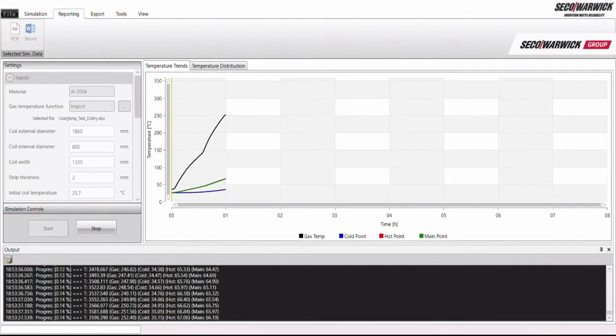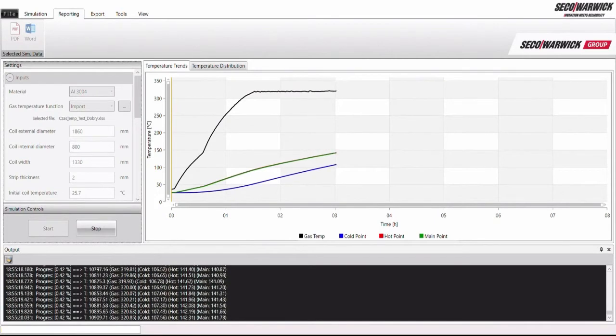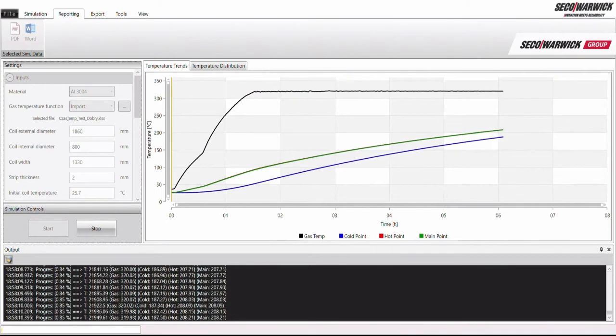The screen shows the real-time coil heating curves. The black line shows the temperature of the furnace heating chamber measured by the regulating thermocouple. The red line, the highest temperature of the coil determined by the simulator. The blue line, the lowest temperature of the coil determined by the simulator, while the green line, the temperature indicated by the so-called virtual control thermocouple.